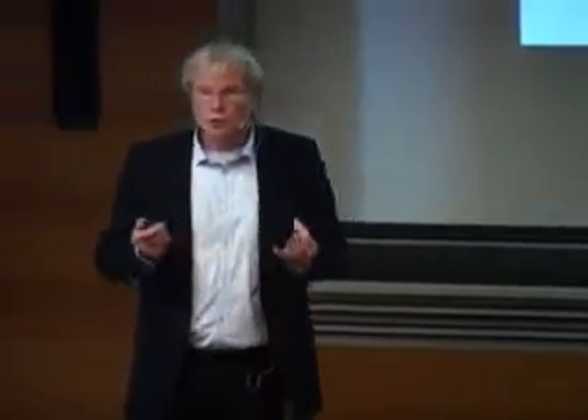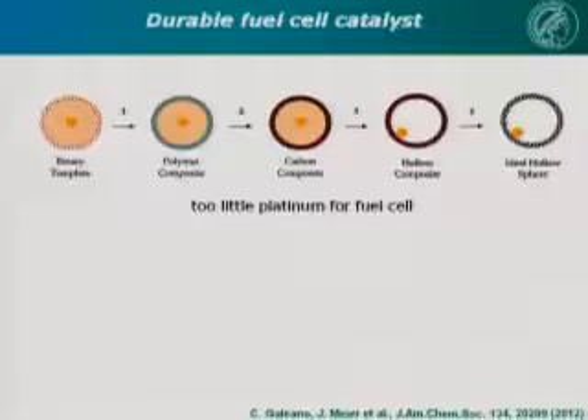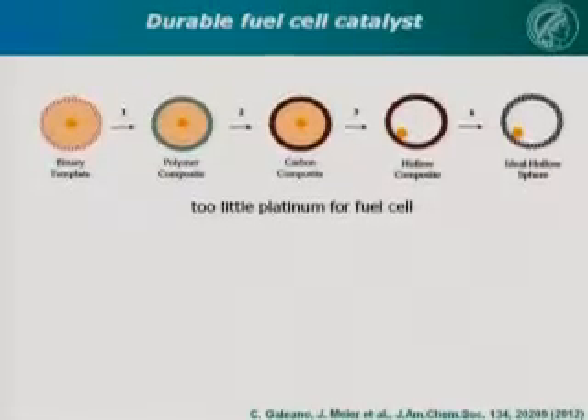And we wanted to produce fuel cell catalyst. And the idea was, well, why don't we just take the very same concept, but put platinum inside, have platinum in carbon, and then it cannot be leached out, or it's more difficult to leach it out because it's stabilized in the shell. Well, it turned out you don't get enough platinum into these shells. Fuel cell catalysts have a typical loading of 50% noble metal on carbon. And it's almost impossible to get 50% platinum by this process into the shells. So these catalysts have mass activities overall normalized to catalyst mass, which is way too low. And so we had to stop this line of work.